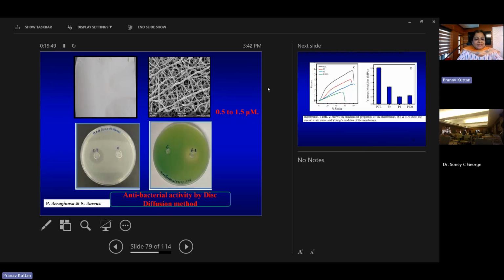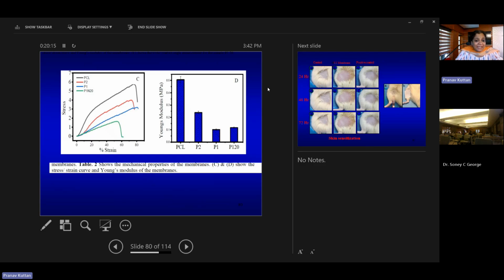So this first one is the electrospun membrane, and the right one is the membrane where we can see the fibers. And since we are planning it for wound healing, because dental wound healing, we tried S. pyogenes, which is found in the mouth. Then S. aureus was also tested, and it is found to be satisfactorily meeting the condition of antibacterial activity. Then we tried mechanical properties, and it was found to have sufficient strength. And we also calculated the Young's modulus of these membranes, and as expected, the PCL membrane had the largest value of Young's modulus, whereas the other membranes had comparatively smaller values.